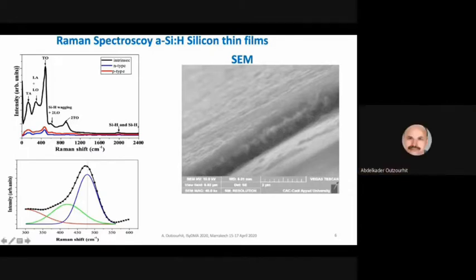This is a bird's eye view of one of the films, the intrinsic layer that was deposited on an underlying fluorine doped tin oxide or FTO coated glass. You can see the FTO layer, and above it you can see the intrinsic hydrogenated amorphous silicon layer, and as you can see, the surface of the layer is also textured. And as I mentioned, since the underlying FTO layer is also textured. Okay. As I mentioned before, this texture enables light trapping within the cell and favors the absorption within the cell,